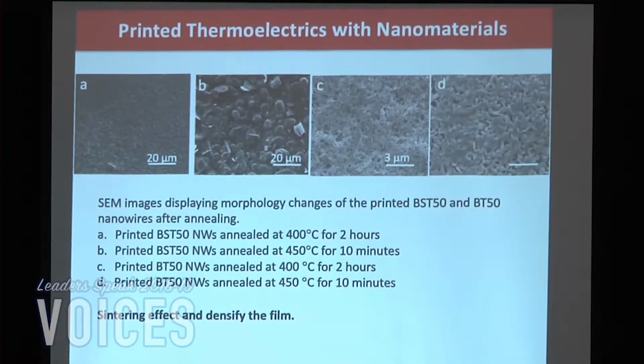But then we also, just like with the graphene electrodes, anneal those substrates so that the morphology changes as well. After we do annealing, you can really see it here in C and D, where the nanowires are printed here, and then they just look like they've kind of morphed together. It helps sinter them, and this sintering effect increases the density of the film and makes it a better thermoelectric material.